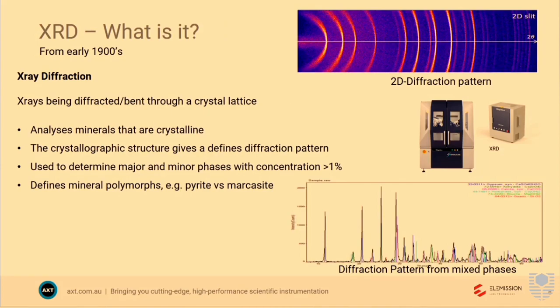So the way that works is you shoot an X-ray at a material, and then the X-rays are diffracted within the material. So what's diffraction? So they're kind of like bent through the crystal lattice. And you end up with an X-ray pattern at the top. So the original XRD instruments, you'd have to move the goniometer of the instrument to detect the X-rays from point to point to point to point. So they were called 0D X-ray instruments.